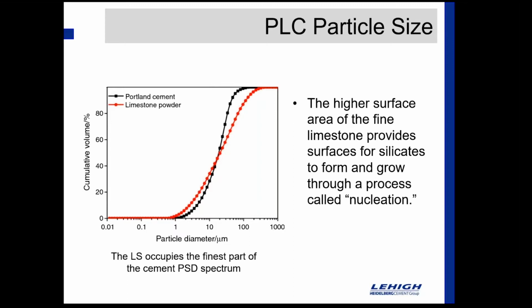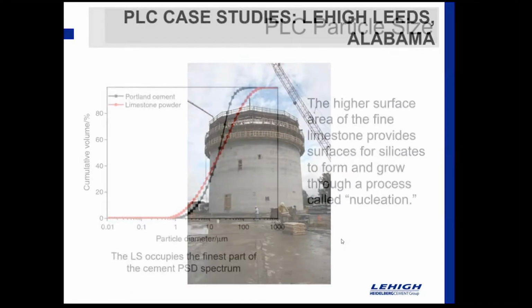And so a good benefit of that fineness increase is that the higher surface area of the fine limestone provides surfaces for silicates to form and grow through a process called nucleation. So essentially it gives more places for that hydration reaction to begin to start.